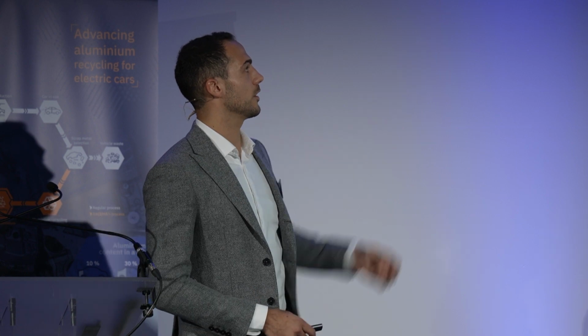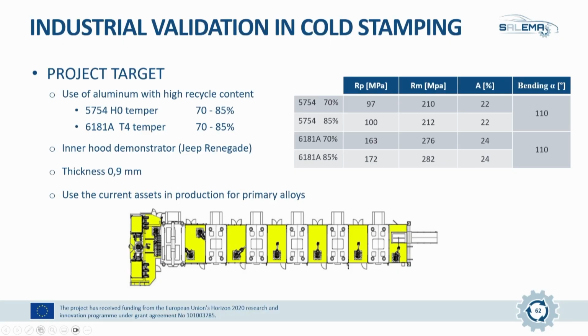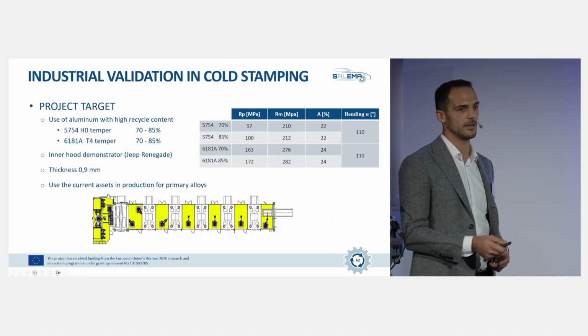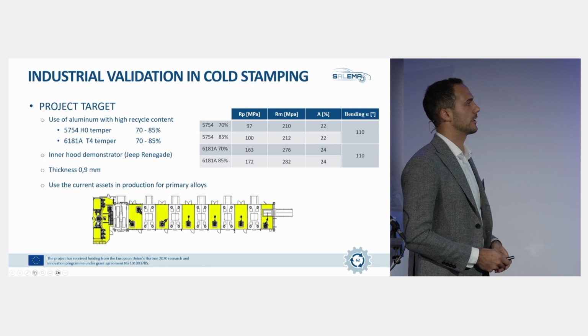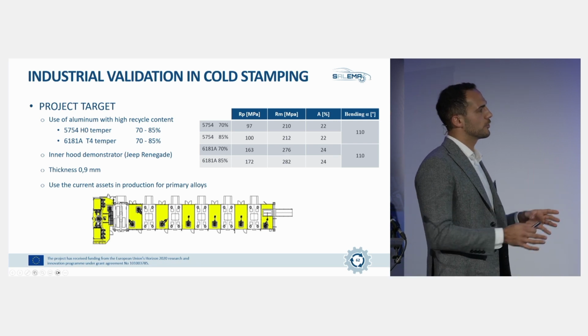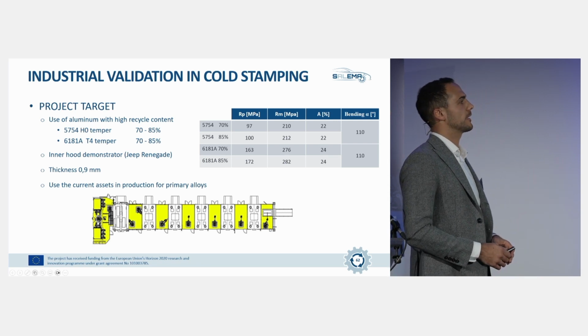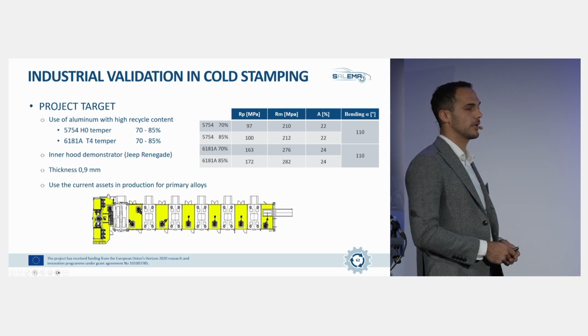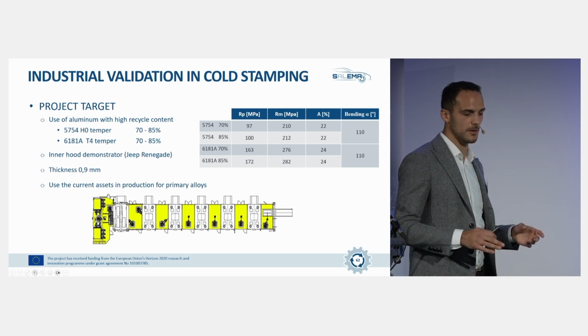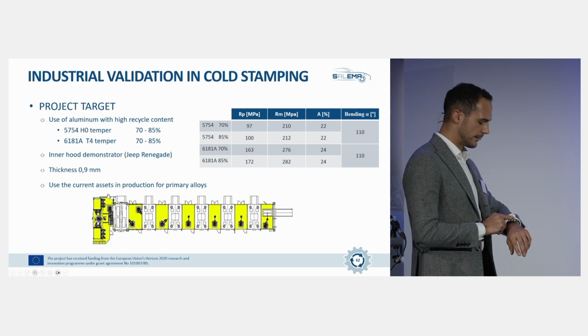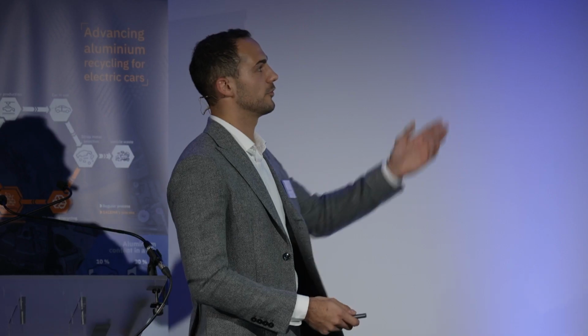We produced it with 2 alloys, one 5000 and one 6000 alloy, with recycled content. The mechanical properties were assessed not at component level but at specimen level, and the results were very good. We produced it with the current stamping plant that we have in Mirafiori, on the same components that make the normal production of the Jeep Renegade.